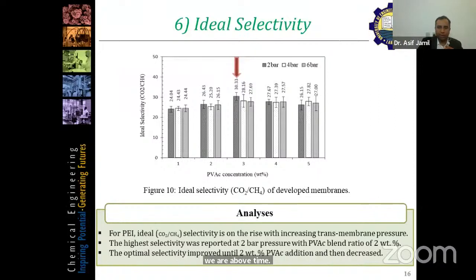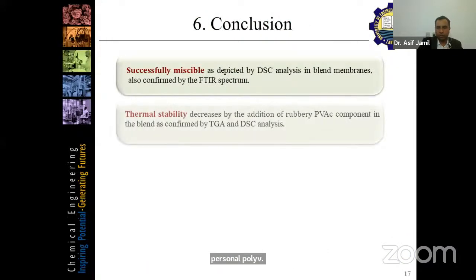So the maximum selectivity we achieved is 30.33 for 2 bar pressure at 2 weight%. So our optimal membrane contains 2 weight% of polyvinyl acetate. And if I quickly go through the conclusion, we successfully achieved miscibility of our 2 polymers in the blend.